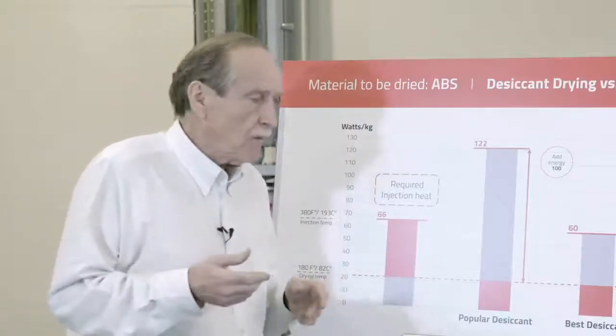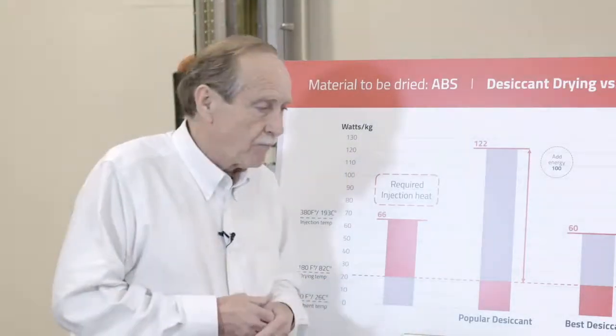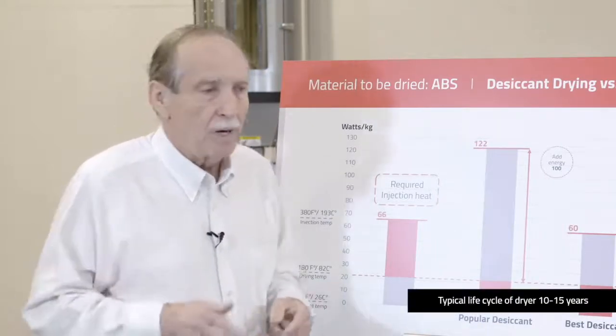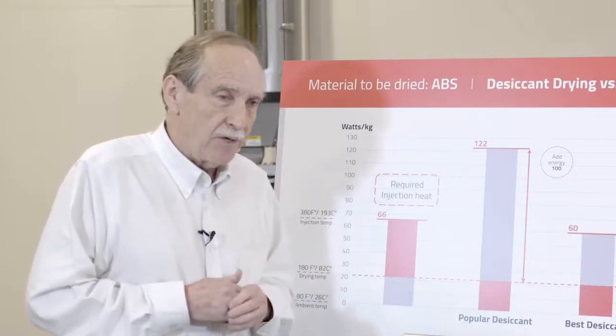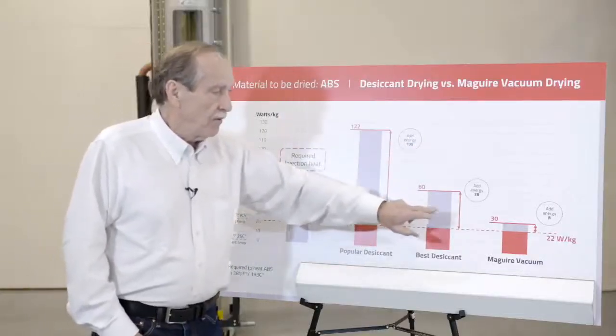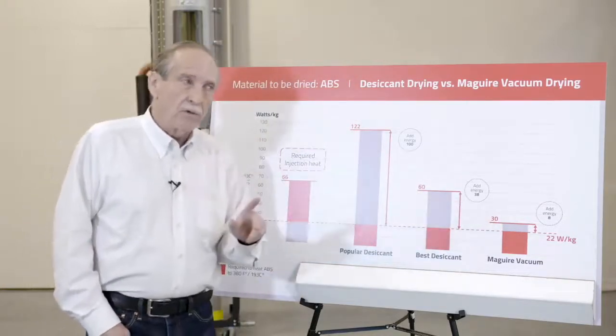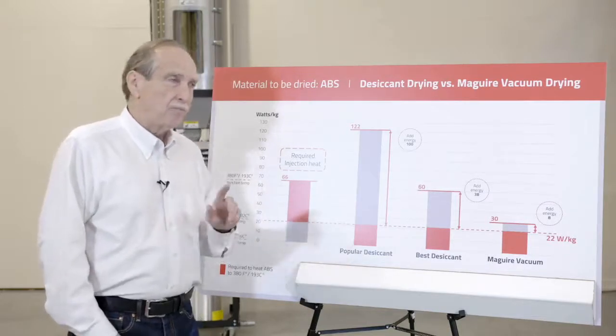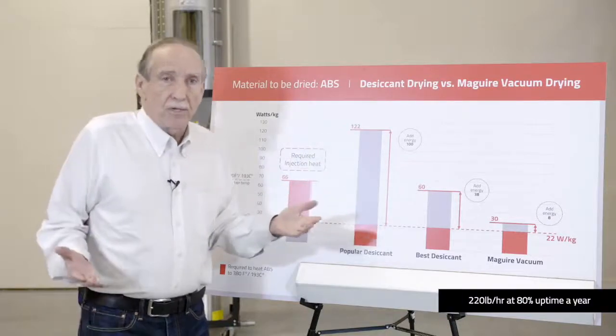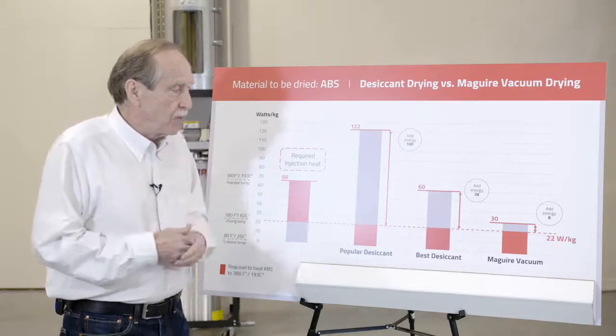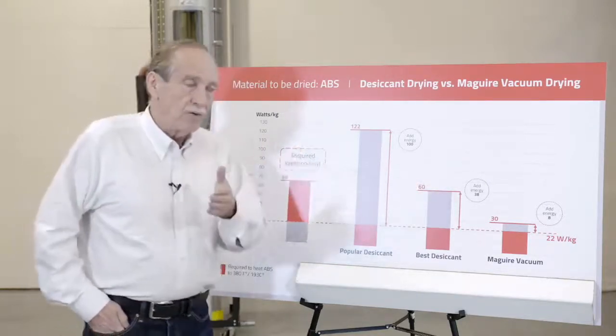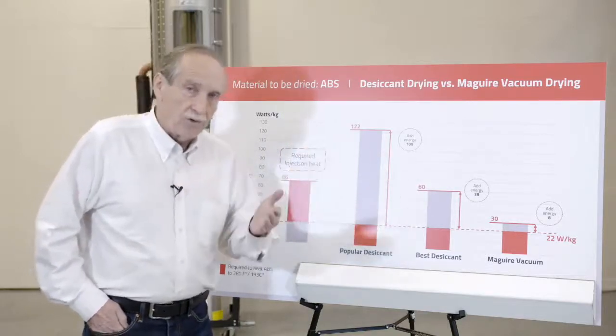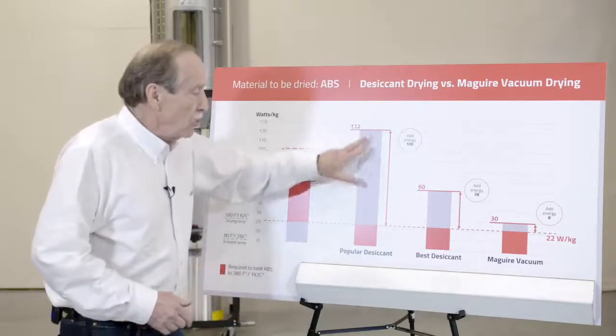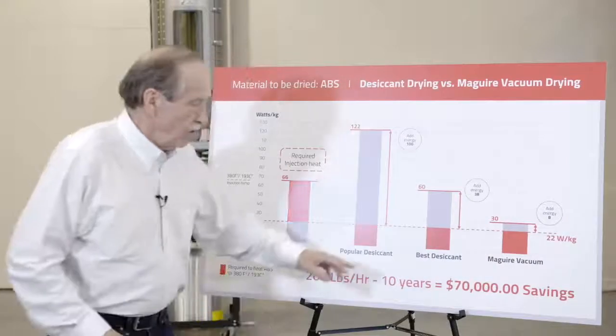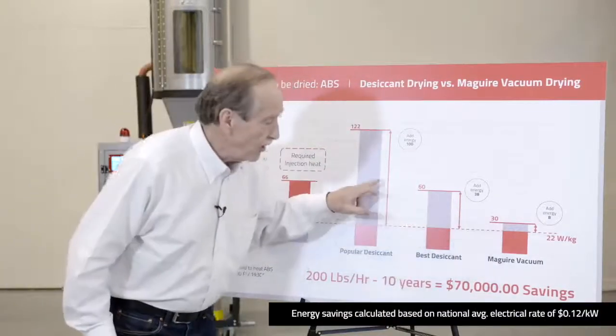When you buy a dryer, I'm sure you assume you're going to have that dryer for 10 years. 5 years would be short, 15 years, we might be pushing it. I'm going to say 10 years. So you've got a desiccant dryer, and you run it for 10 years, and you run it with this added energy load versus this, and you're running, let's say, 200 or 220 pounds an hour, 100 kilos an hour, and you're running a normal 80% of uptime for the year, round-the-clock operation, and you calculate those savings based on what the electric company charges you, you will, with this dryer versus this dryer, and let's just say these are $15,000 dryers, you will have spent $70,000 more here than you spent here. $70,000.